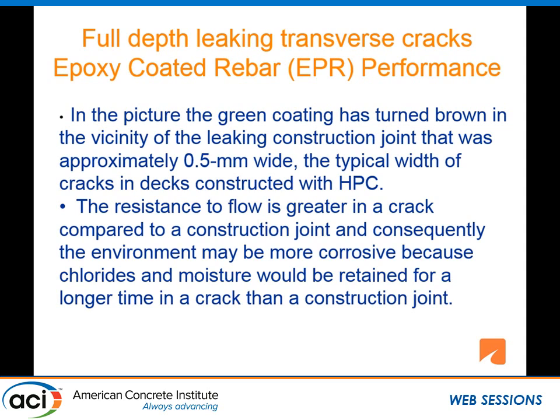The resistance to flow of your chlorides and moisture through a crack would actually be greater than through this construction joint, which is pretty much a straight shot. So there, you should be getting even worse corrosion where you have your full-depth cracks.